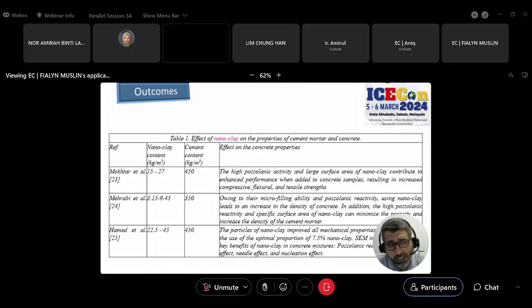The first is the effect of using nanoclay on the properties of cement, mortar, and concrete. So in this table, we summarize the top three of the many references that used nanoclay, with nano-clay content in weight of kilogram per cubic meter between 15 all the way to 27. So Mokhtar et al. used 15 to 27 kilogram per cubic meter of nanoclay content added to a cement content of 450 kilogram per cubic meter. Their outcome and its effect on the concrete properties, they observed that the high pozzolanic activity and large surface area of nanoclay contribute to enhanced performance when added to concrete samples, in turn resulting in increased compressive, flexure and tensile properties.